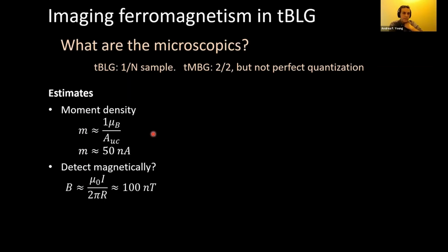There are certain features in all of these moire systems that are reproducible. So superconductivity is not that hard to see, right? At least in some form, but it's a little different every time. It's not like you're going to measure two samples and get the same TC to within 5%. Certainly for these magnetism samples, you see the evidence of disorder relatively sharply. Besides the fact that it's hard to remake the same sample, you see these Barkhausen jumps, right? That's telling you something about disorder, and they're actually quite reproducible in transport. So it looks like it's structure.